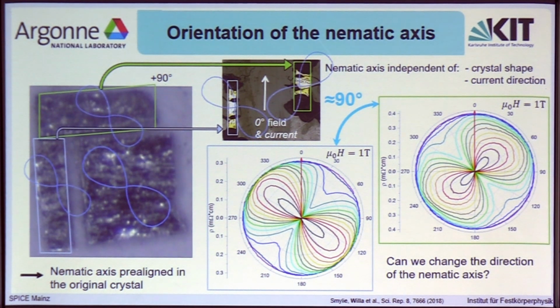Maybe there is some strain in the sample that's already coming during the growth. Maybe the intercalation is not uniform, making the nematic axis align by preferred direction. So we asked ourselves whether we could actually change this nematic axis by counteracting this supposedly internal strain of the sample.